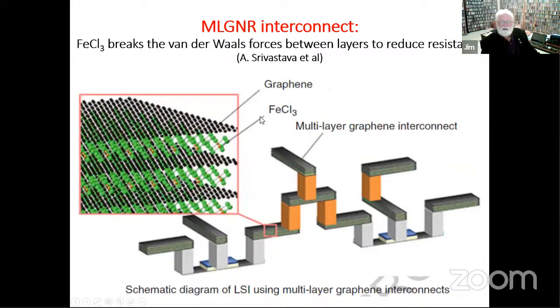And I mentioned that if you put multiple layers, then the property of the graphene starts to be lost. But if you put a layer of something like ferric chloride, this is the first material I heard of, but there are other materials that work the same way. That breaks the van der Waals forces between these so that you get the ideal property of this graphene layer and this graphene layer and this graphene layer. So you get effectively single graphene layers in parallel, which is what you want.